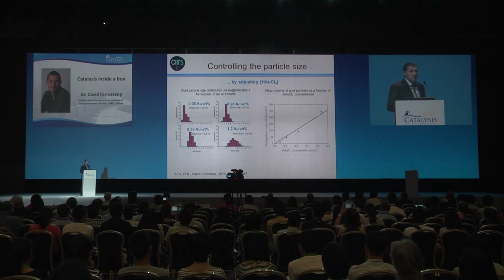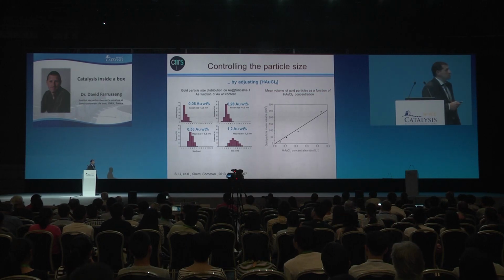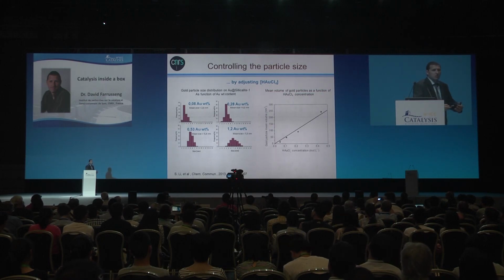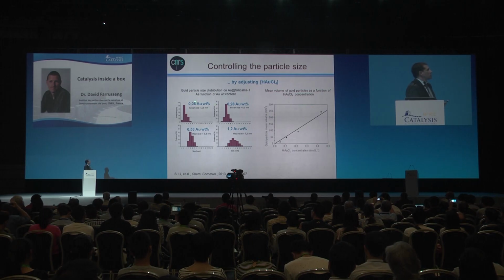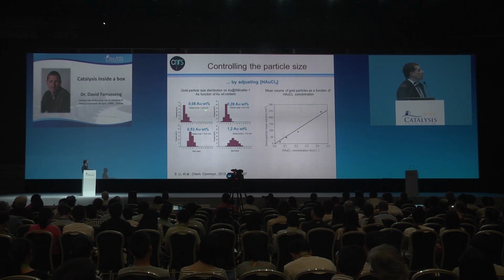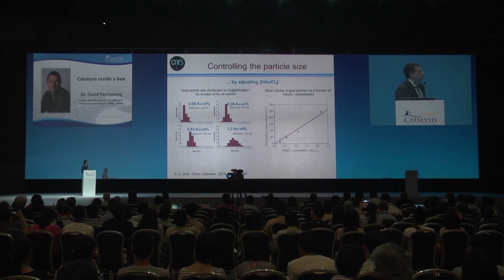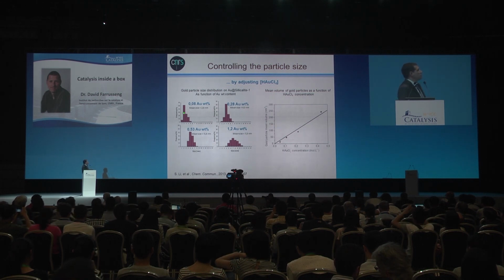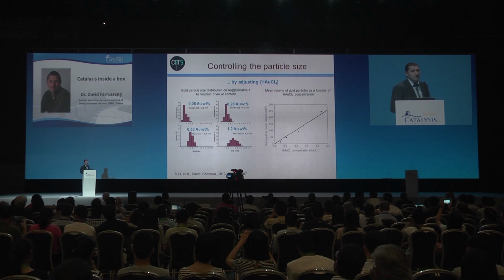We can easily vary the size of the nanoparticles by adding more gold to that. For example, for a gold content of 0.08 weight percent, we have 2.6 nanometer, and for 1.2 weight percent, we have a size of 7.5 nanometers, and you can see, always with a sharp distribution.